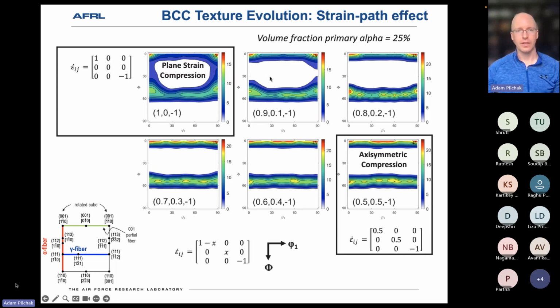If I now relax that perfect plane strain compression and I allow 10% of the strain to be accommodated along the original bar axis, I immediately shut off that pathway that gets orientations from the gamma fiber up to the rotated cube orientation, but I still am developing a relatively strong rotated cube orientation there. Now, if I go to 20%, I let 20% of the strain be accommodated by extension along the bar axis. I'm reducing the intensity of the rotated cube orientation a bit. I'm gaining a little bit of this 111, 110 texture component. So things are getting better.